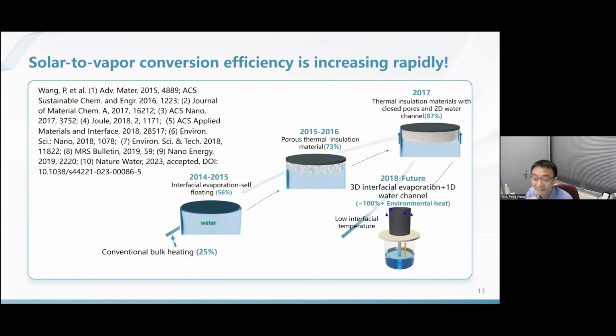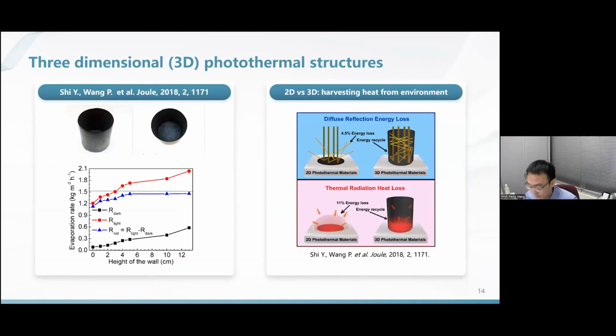Now for me, the most exciting part in the field happened in 2018, when a couple of very nice three-dimensional evaporator designs were reported. I used one of our works to demonstrate why this three-dimensional structure is very significant. Now, if you can utilize solar energy to its full potential, 100%, your water evaporation rate will be at 1.5. That's a maximum. That's a ceiling. Now take a look at this red curve here. You see, in our system, we could achieve an evaporation rate much higher than 1.5, as high as 2.1.